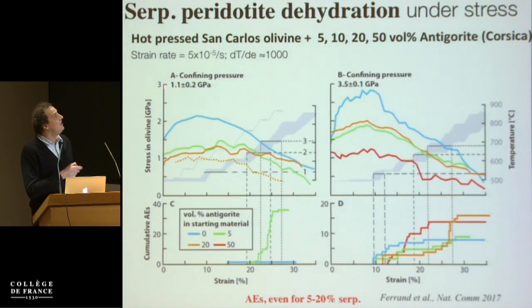So if you do the same thing now at 3 GPa, you have similar behavior. Interestingly, here we didn't have any acoustic emission for large amounts of serpentine, and I can discuss that in some detail if you want. But in this case, we do see clearly the link between dehydration of serpentine, even for very limited amounts of 5 or 10%, or 20%, you see small laboratory earthquakes being triggered. And we also see, and this we don't understand, some acoustic emission being triggered in pure olivine.